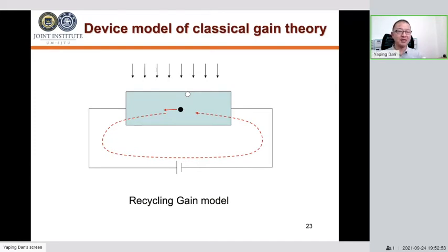The widely accepted concept is that light generates electron-hole pairs. One type of excess carrier is trapped by surface states, and the trapping time can be very long. The other type of carrier is driven by the electric field and circulates in the circuit many times, because the applied electric field is very big, so they transport very fast and can circulate the circuit in a very short time.